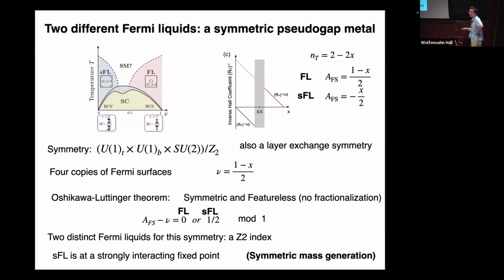So what's the reason? It turned out it's because of this interesting symmetry. For this symmetry, if you apply the Oshikawa-Luttinger theorem, as Subir mentioned, you will find the Fermi surface volume minus the filling per flavor. Oshikawa told us this is a quantized object, but in this system it's quantized to be 0 or 1/2 mod 1. So there is a Z2 index for symmetric Fermi liquids. This Fermi liquid corresponds to the non-interacting fixed point. This second Fermi liquid turned out to correspond to a strongly interacting fixed point. So it's different from the textbook introduction of Fermi liquids. I think this concept is also related to symmetric mass generation, because this phase is possible only because of the strong four-Fermi interaction. So it's beyond any weak coupling theory, any mean field theory. And we have a theory of how these two Fermi liquids go to superconductivity at a lower temperature.